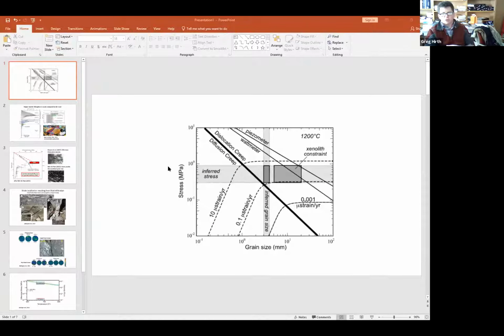Right. All right. So here we are at figure 10. And so what this model is showing is, if you look at the best fitting models that Andy produced, they would end up with an inferred stress like this and an inferred grain size if it's diffusion creep, or just a stress level if it's the dislocation creep. That's what you would get out for a temperature of like 1200 degrees C.